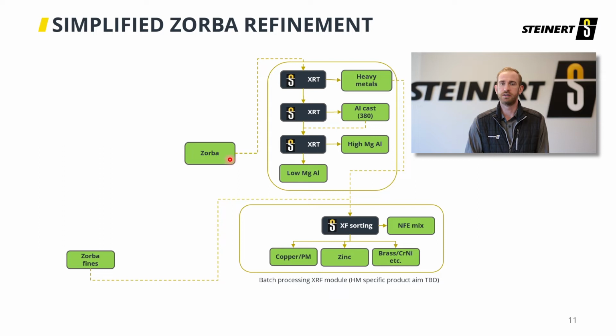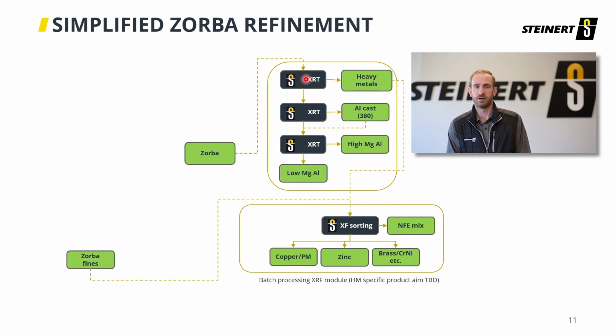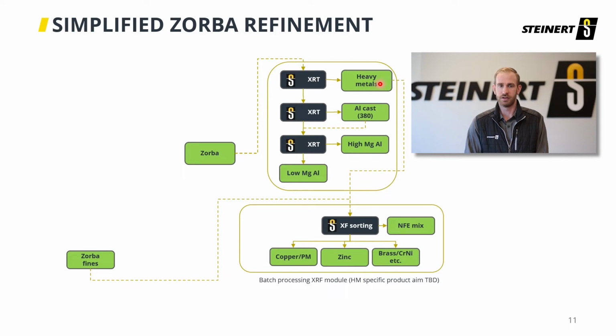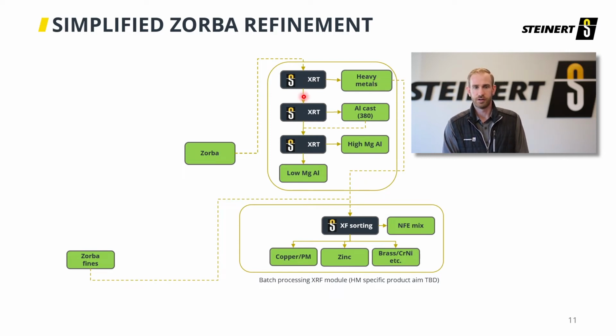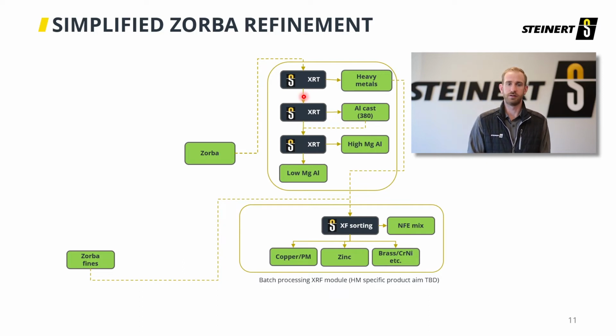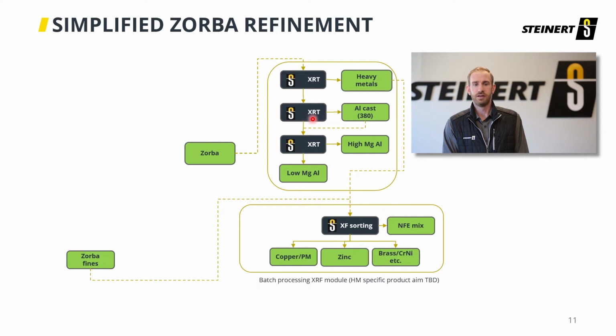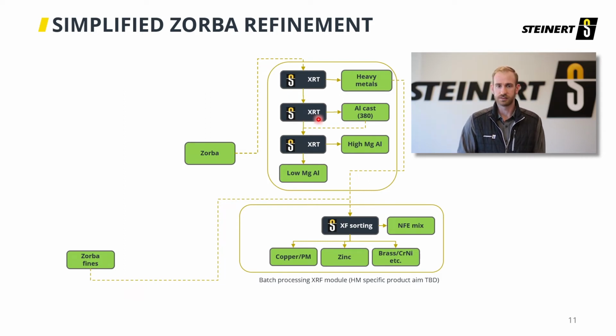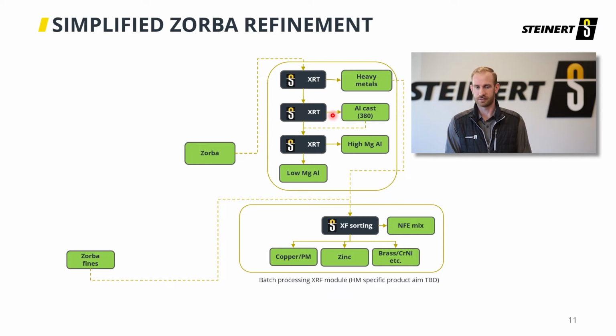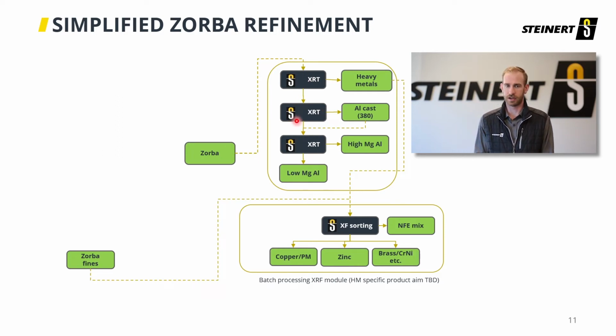So we have our Zorba here. That's a product of our recovery process off the eddy currents. And we're going to send that into our first step, XRT. This sort is going to be separating heavy metals from light metals. So here's your heavy metal product, and we're going to follow that flow chart in just a second. But your other product off this first step will be your Twitch, your aluminum fraction, this mixed aluminum fraction. This can go into your second stage, your second sorting XRT, which is going to be separation of cast and sheet or cast and wrought. And then a final third step could be concentrating your magnesium content or separating out your magnesium content. So those 3 XRT steps are your typical refinement flow.